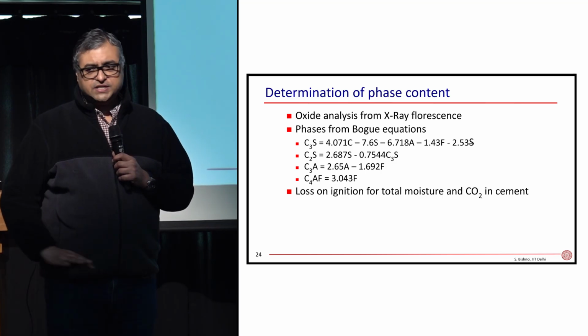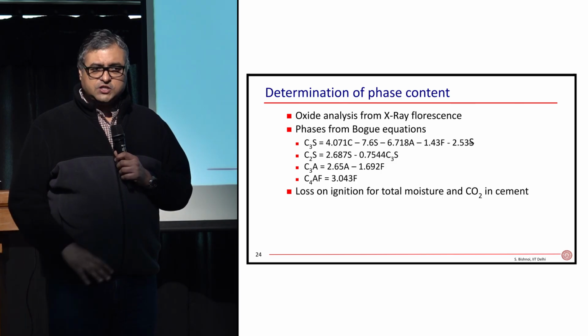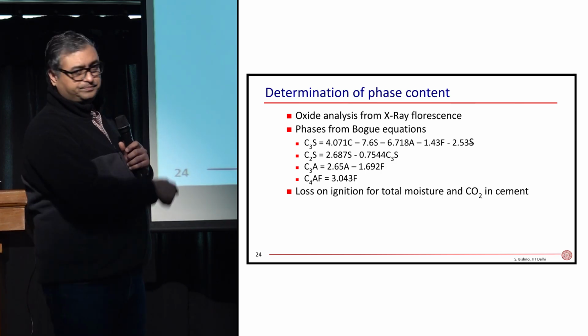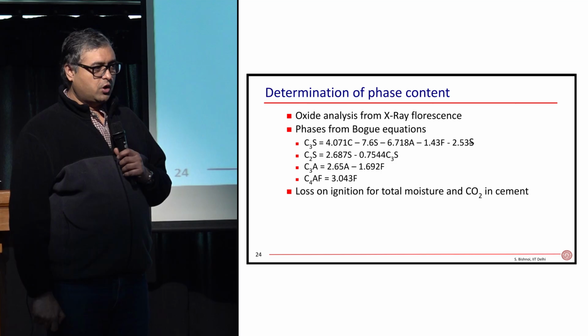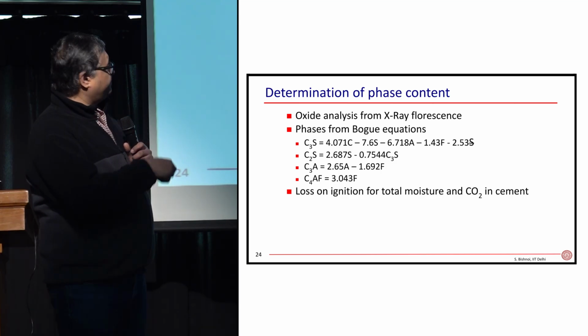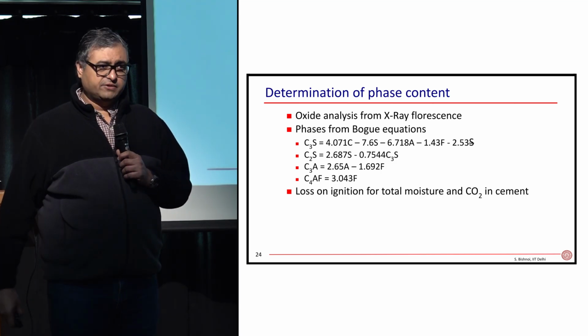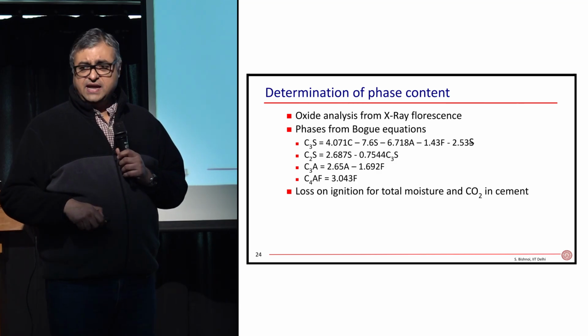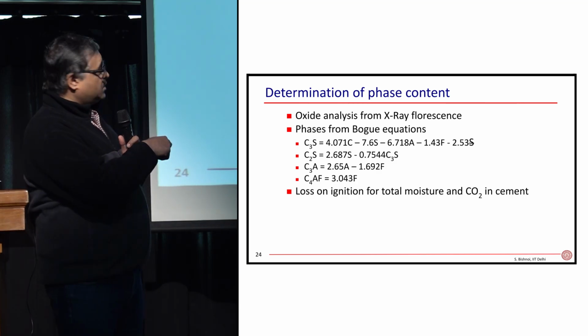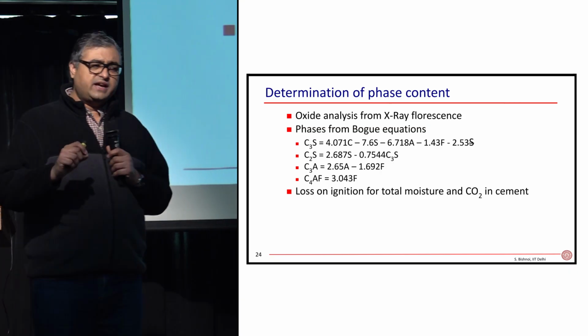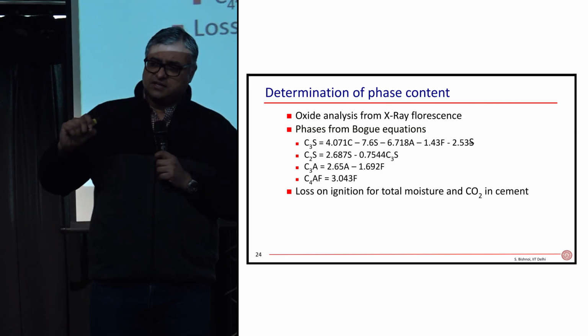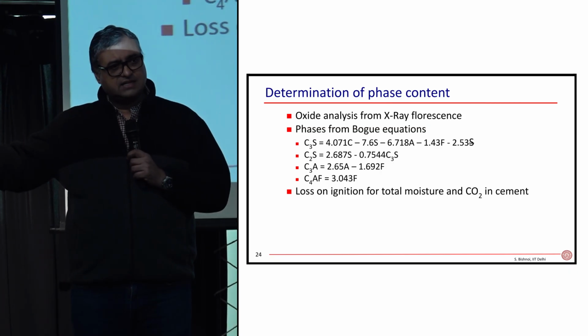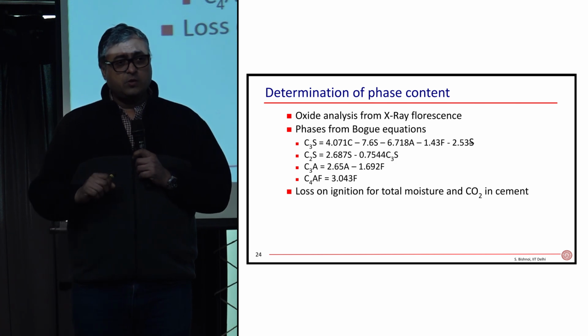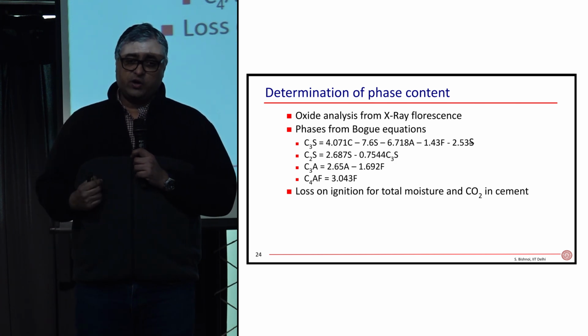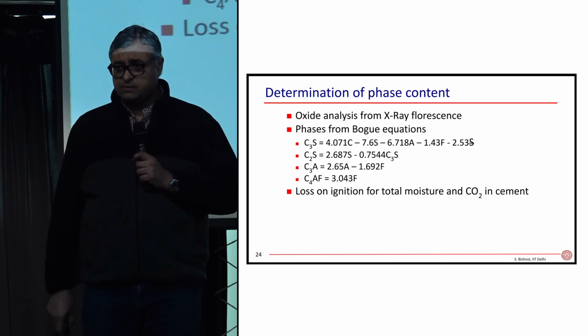Now I know how much iron, how much alumina has gone into that — how much Al2O3 has gone in that. I subtract that from the total alumina that is available and find out the remaining alumina, and from that I can calculate how much C3A is there, assuming that the formula of C3A is C3A, CaO whole thrice, Al2O3. Assuming that the alumina is present only in C3A and C4AF, I can find out how much C3A is available.